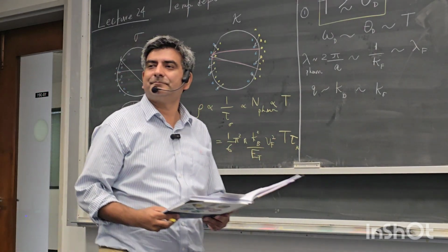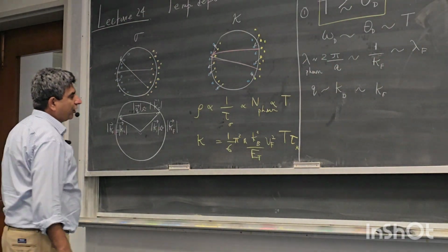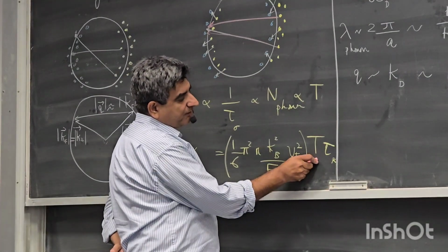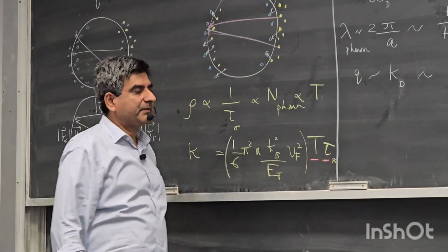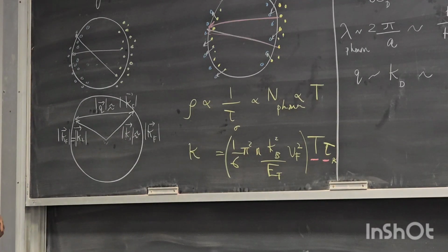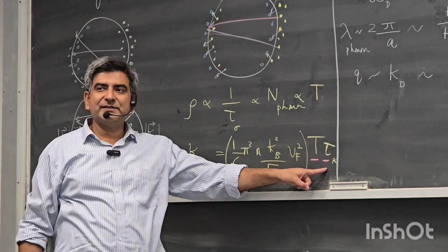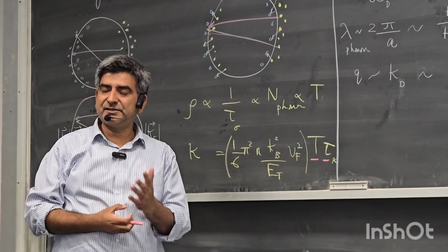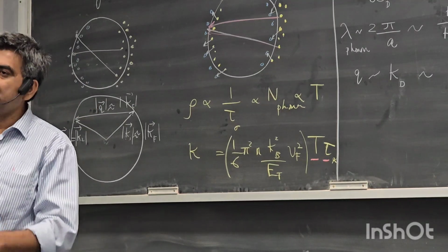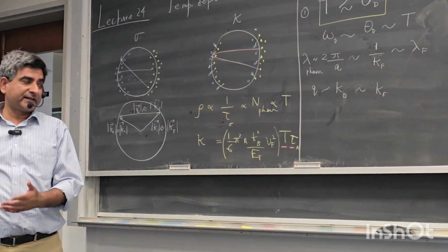Okay? So this is the formula that we have for thermal conductivity. All of this is a constant here. Now, if you observe, there's a product between the temperature and tau kappa. Tau kappa is the scattering due to the phonons that are available that can affect this relaxation process. Now, this tau is inversely proportional to the number of phonons that are available. And we know that those phonons have the correct wave number and the correct energy, so all of them will contribute to the relaxation process.